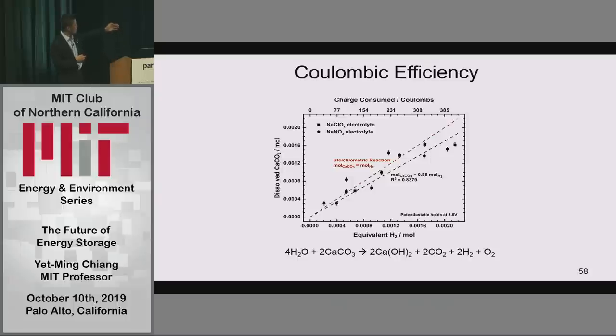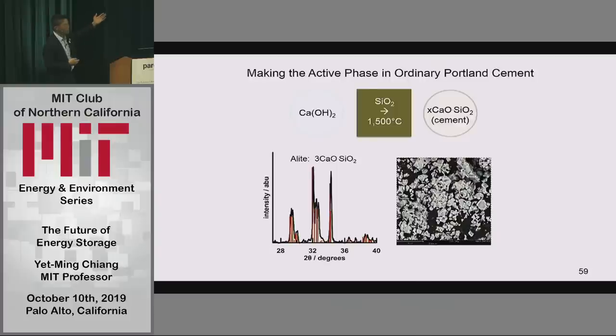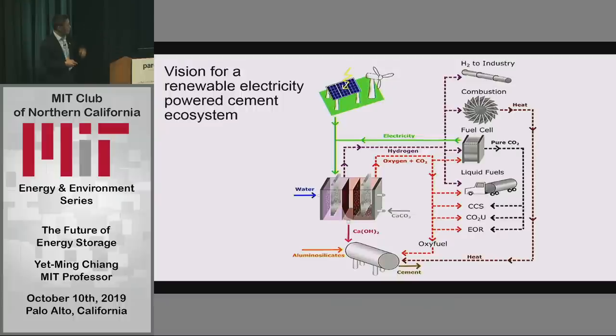And the overall reaction is we have calcium carbonate producing calcium hydroxide and releasing three gases. You know, we have CO2, we have hydrogen, and we have oxygen because it's an electrolyzer at the same time. Okay. So what we've shown is that this material can now be used to make the active phase in ordinary Portland cement, OPC. When you hear ordinary Portland cement, the O is capitalized. It is not an adjective, it's a name. It's a noun. The ordinary Portland cement is the product. And so we've done the first step in showing that this could be used in order to produce cement.